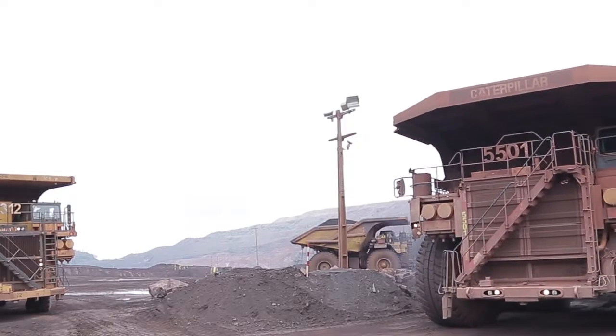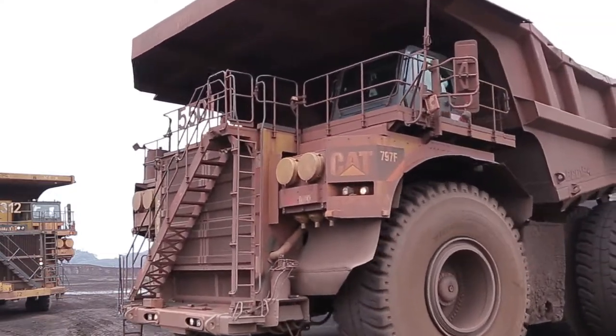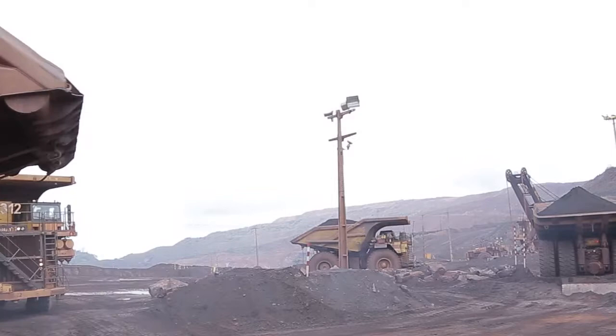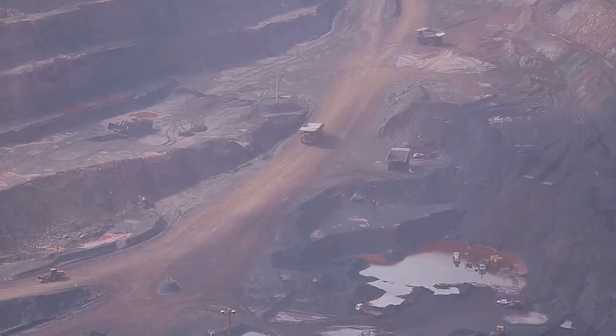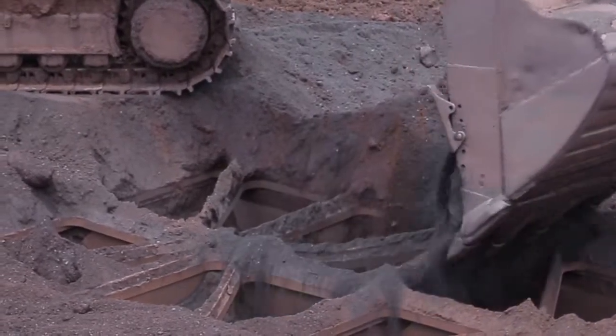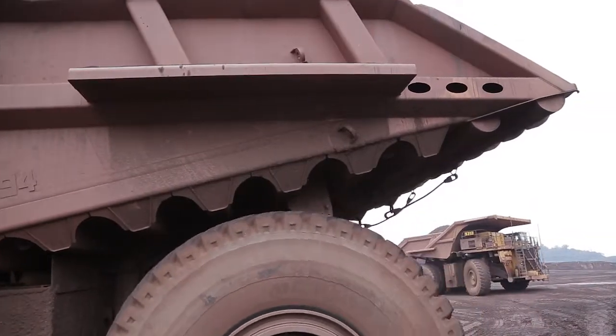In use, the new screener has worked exactly as intended, and Vale has seen an incredible reduction in downtime. The implementation of the screener in one of the crushers showed a decrease of 92%. The screener's estimated lifespan is 2 years in 24/7 operation, which is a long time in mining terms.